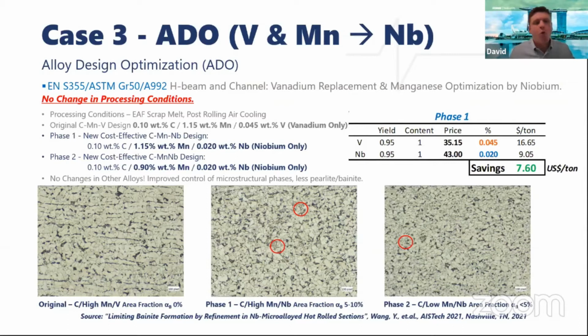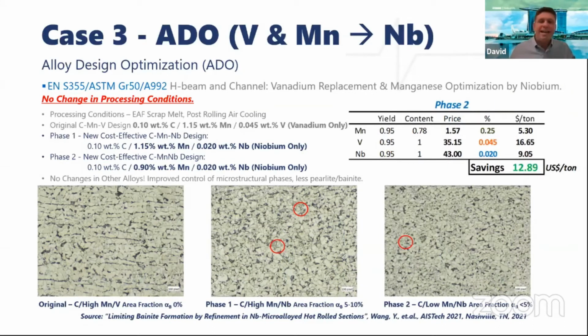And further on, we could achieve slightly higher strength level than before. So we could manage to reduce the manganese as well, which brought not only cost reduction, but also a better microstructure control for improved yield to tensile ratio. Using the same 200 ppm of niobium, no vanadium, and only 0.9 weight percent manganese, we could manage to achieve $12.89 per ton cost reduction, which was very impressive. And at the same time, even improved the quality of the final microstructure, as you can see in the pictures.